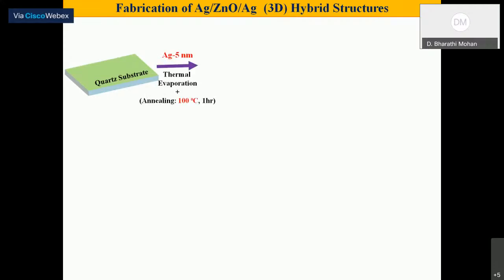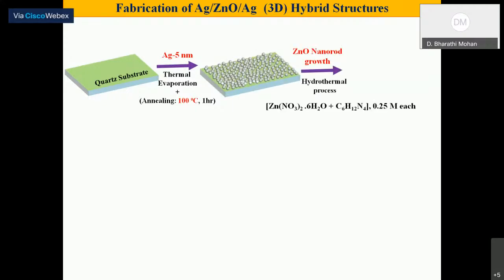Then how to prepare the 3D substrate? We have fabricated 3 different 3D hybrid structures, and here I am giving the schematic picture of the fabrication of the silver-based 3D hybrid structure. Initially, we took a quartz substrate and deposited a silver thin film using a thermal evaporator and annealed it at 100 degrees Celsius. You get nanoparticles, and then this substrate has been used to grow zinc oxide nanorods using a hydrothermal process, and you can see that the zinc oxide nanorods grow vertically.